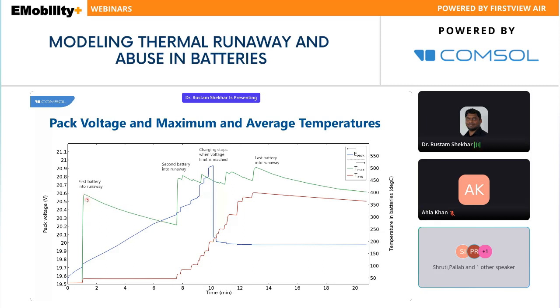So this is the temperature which you can see. First thermal runaway happened, and the temperature reached 350 degrees Celsius. Then a second thermal runaway and second trigger happened, and there is a consecutive failure happening, and ultimately it will go to thermal runaway and start cooling. So we can observe the T max and T average.